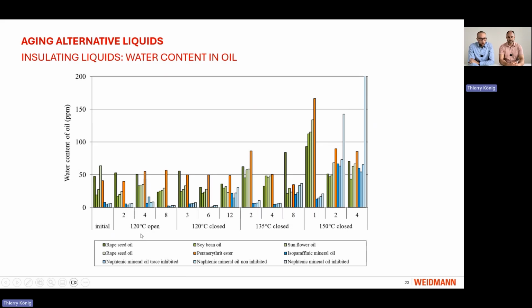When we compare now the 120 degrees open system to the 120 degrees closed system regarding the water content, we can see here the water content in the mineral oil in the open system does not have a big change, but in the closed system we can see an increase towards the end of the test. So in this open system, the water somehow disappeared over this experiment.